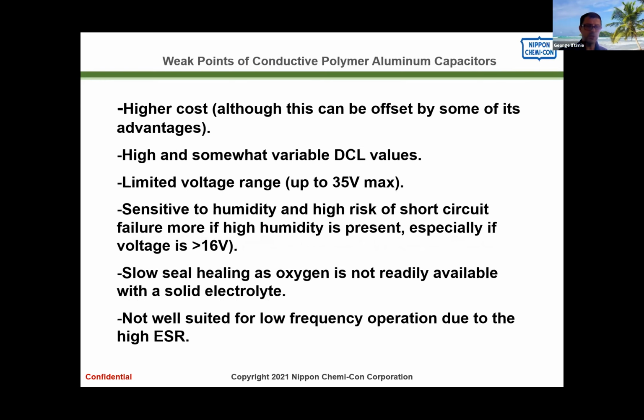Leakage current is one big issue that polymers have. It is significantly higher, usually 3 to 4 times higher than an electrolytic capacitor or a hybrid, even at steady state. And it can also be unstable or variable. When you have an electrical stress, ripple current or voltage, on an electrolytic capacitor, you'll see that represented by a spike in the leakage current. And this is why we refer to the leakage DCL value as kind of like a snapshot into the health of the oxide layer. A poor, degraded oxide will invariably have a higher leakage current value.